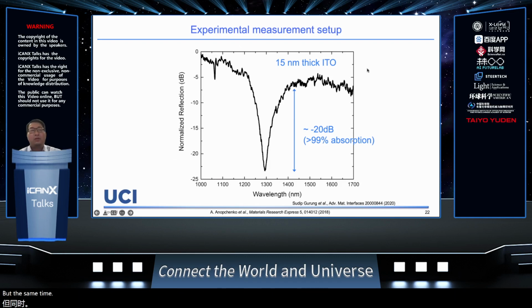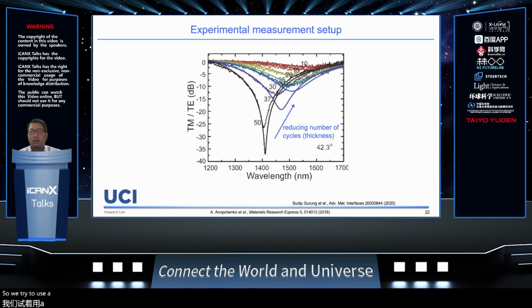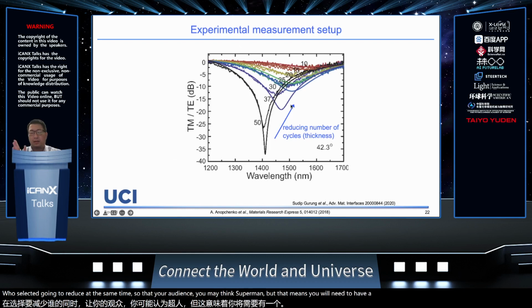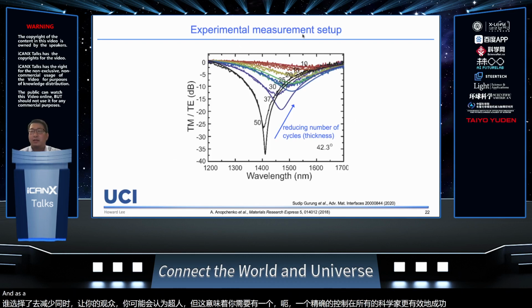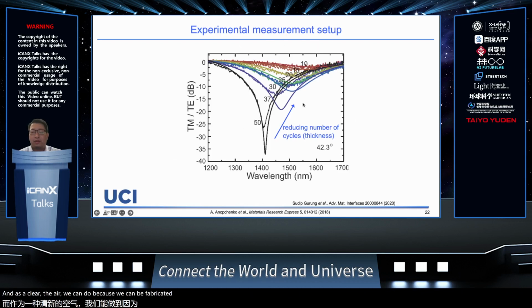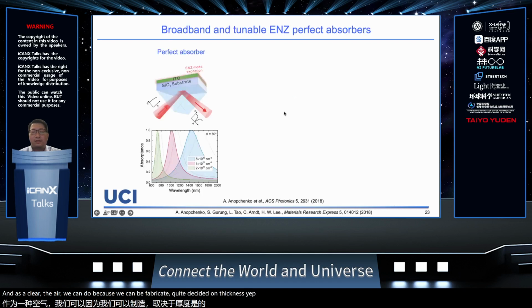At the same time, I mentioned that this excitation really depends on the thickness as well. So we tried to use ALD to make different thicknesses of the material. You can see that by reducing the thickness, your coupling will significantly reduce, and at the same time your ENZ wavelength shifts. That means you really need to have precise control of the thickness in order to excite this mode efficiently, and that's exactly what ALD can do, because we can fabricate quite precisely on the thickness. Then we're able to demonstrate, for example, making this a perfect absorber, as I mentioned. Using one layer, you can absorb almost 100% of light.